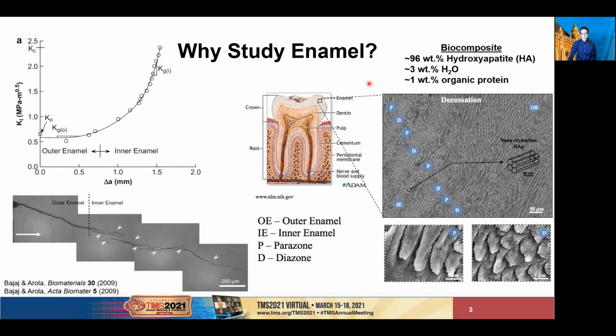Why study enamel? As covered in the earlier presentation by Professor Arola, it is a remarkably tough and crack-resistant biocomposite made of roughly 96% hydroxyapatite mineral, 3% water, and 1% organic protein by weight. It is the outermost surface of our teeth and is approximately 1 millimeter thick for humans. Remarkably, it can withstand many cracks without completely failing, thanks to the myriad toughening mechanisms at play, including crack bifurcation, crack deflection, and microcracking. This results in what is known as rising R-curve behavior, meaning that the crack growth resistance actually increases as the crack grows from the outer enamel surface and extends inwards, with the most significant improvement occurring in the inner enamel. The reason for this behavior is the hierarchical microstructure.